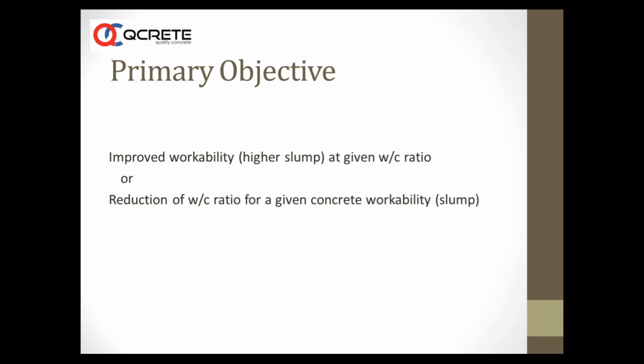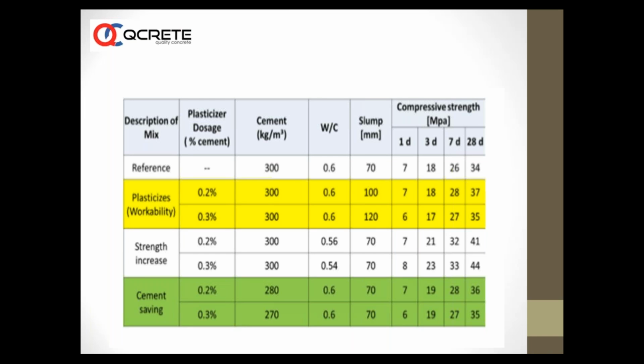The primary objective of using these materials is to improve the slump, make the concrete fluid, or adjust the water cement ratio. One example: these tables were very famous in the 1990s, comparing a reference concrete without admixture to a plasticizer that increases workability, a plasticizer that increases strength, and a plasticizer that gives cement reduction.